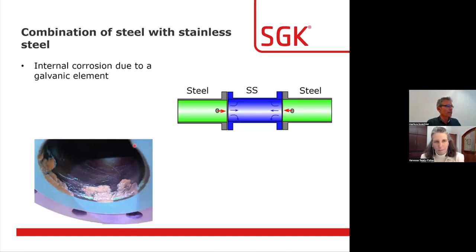To give you another example, this is a valve between steel and stainless steel tubing. Usually these valves are coated with some fusion bonded epoxy coating, which has been evidently mechanically damaged here. And having the damaged coating of steel connected to the stainless steel, again -700 here, -200 here, gives you a battery, gives you corrosion. And what we observe is that you can happily perforate about 0.5 centimeter within 5 years of operation, simply due to the galvanic corrosion between the steel and the stainless steel in that installation.